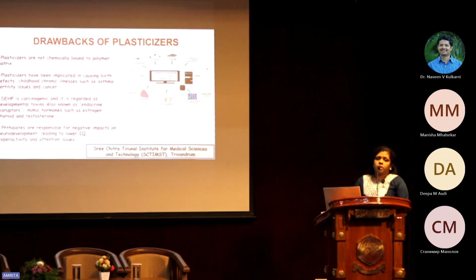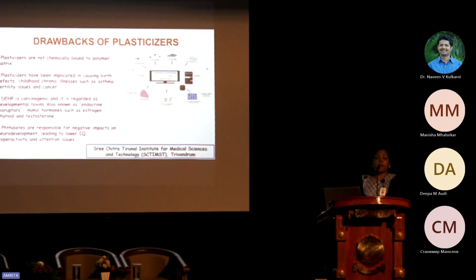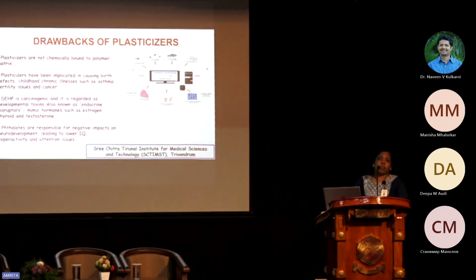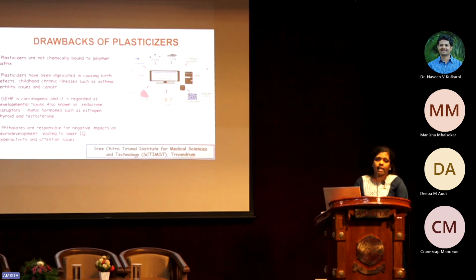So there are many disadvantages. In the case of a plasticized polymer matrix, the main problem is that the plasticizer is only physically interacting with the polymer matrix. There is no chemical linkage between the plasticizer and the polymer. So the plasticizers easily migrate from the polymer matrix and then leach into the immediate microenvironment. That will cause a lot of toxicity systemically, in the systemic circulation. The plasticizers have been implicated in causing birth defects.